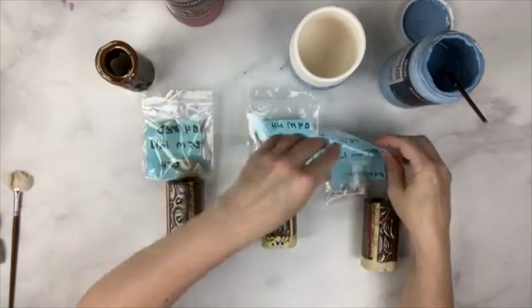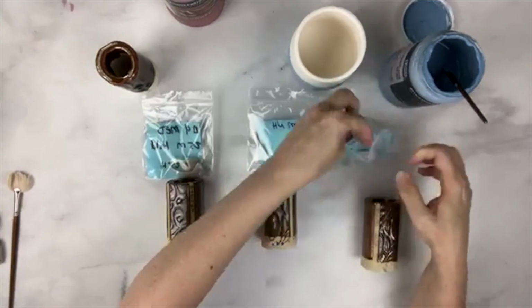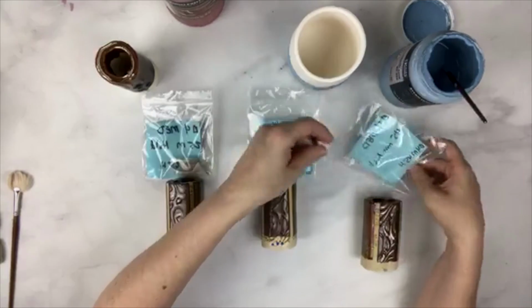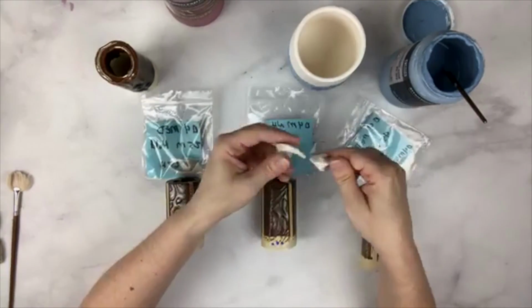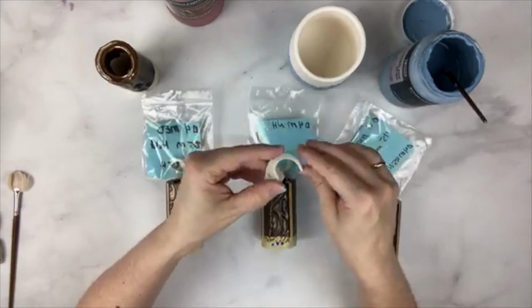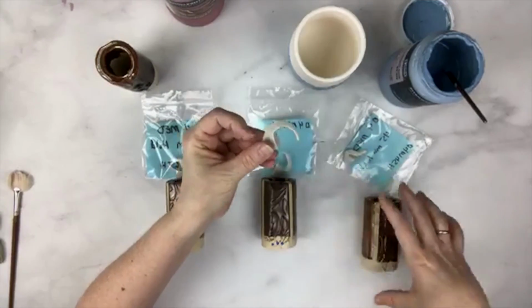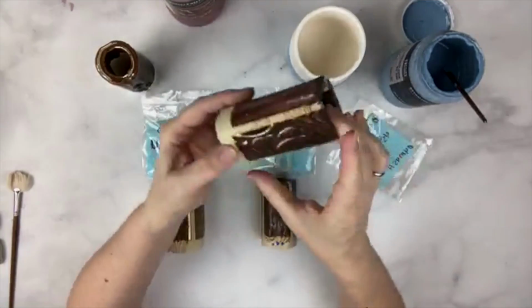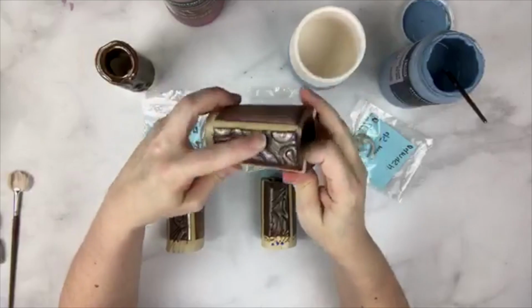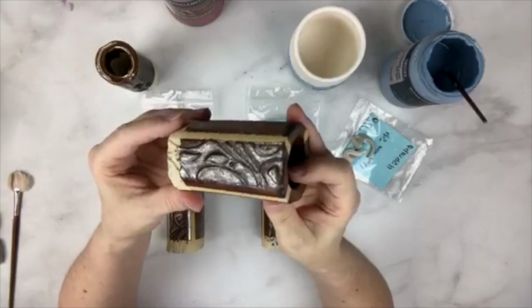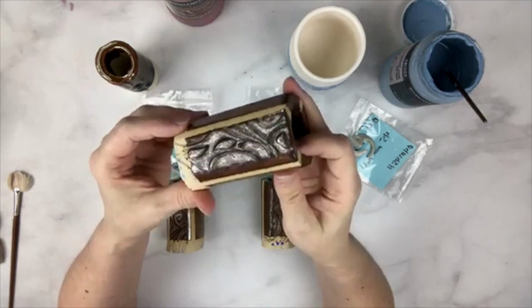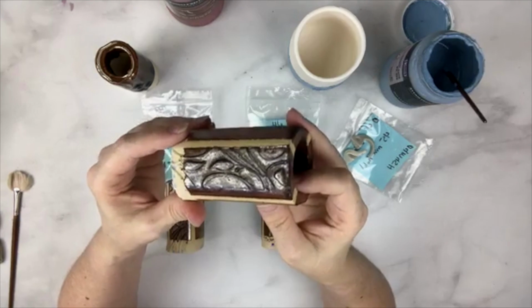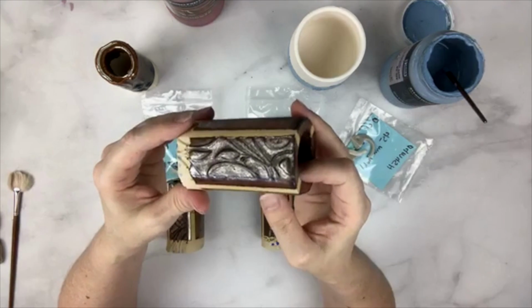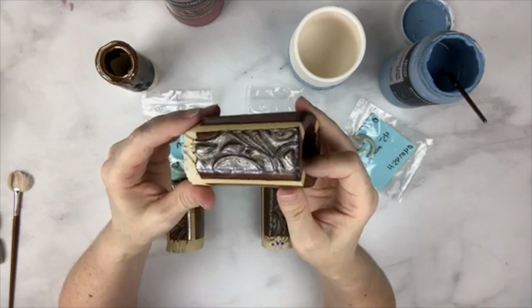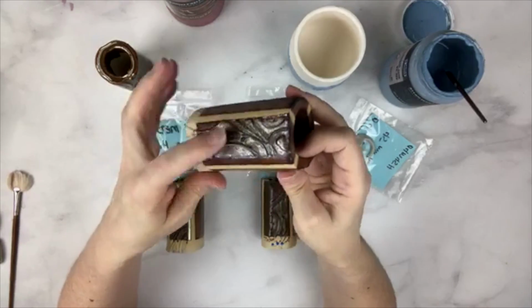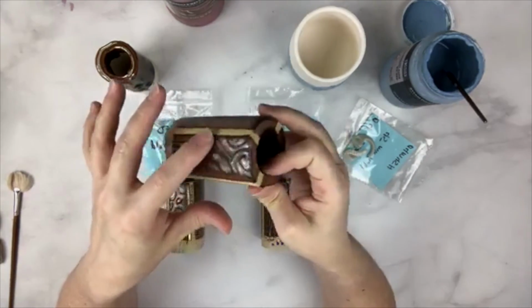And then she also did cone 4 with a 45-minute hold, at which cone 5 is fully bent. That is a full cone 5. And 3 coats right here looks about how we would expect a cone 5 to look. So even though the kiln was programmed for cone 4, a 45-minute hold means that the heat work takes it up to a cone 5, and we get pretty much what we would expect to see from a cone